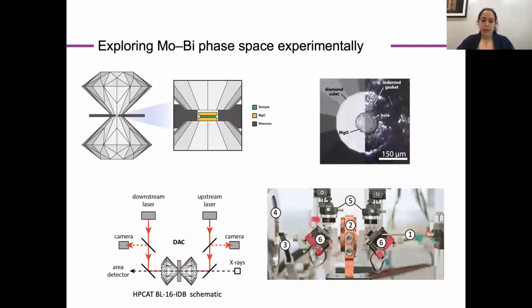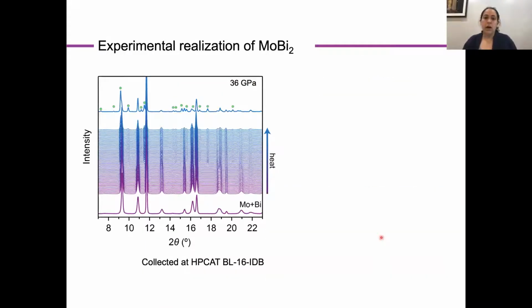And at this beamline, we can heat our samples up to thousands of degrees Kelvin with these lasers, while simultaneously performing microdiffraction on the heating spot to rapidly scan through temperature, pressure, phase space, providing the perfect complement to those high throughput computations I showed you on a previous slide. And so I took a diamond anvil cell containing molybdenum and bismuth to HPCat and pressurized it up to 36 GPa, so right around that 40 GPa conditions that I was showing you that I addressed computationally.